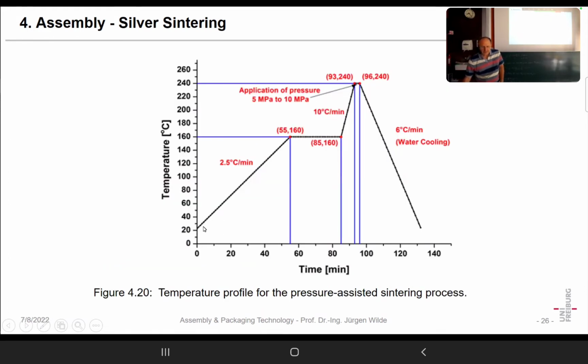That's a typical process. We have a limited rate of heating. Again, all of the solvents must gas out, for instance. Then we have a certain preheating time. It's possibly some kind of activation. Then we heat faster, keep the pressure. In that example, it was 5 to 10 megapascal, which is normally too low. And then we keep it for a few minutes and cool at a limited rate.